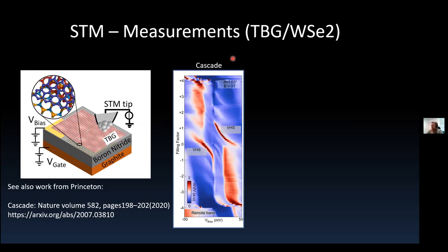So this is now our spectroscopy as a function of filling factor. It's a complicated diagram, but you see 2 Van Hove singularities, and when one approaches the Fermi level, it splits into branches. For the experts in the audience, this is basically a cascade that was reported in work from Princeton. So for us, this immediately became apparent when we switched to this new substrate.